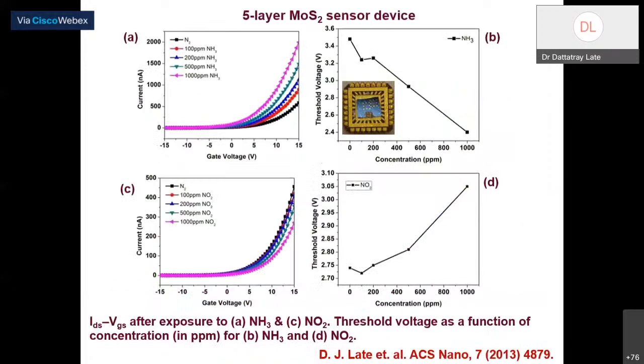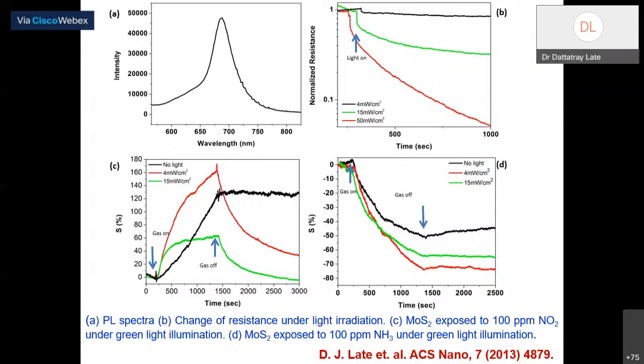One of the parameters which needs to be optimized is the response and recovery time. It's also very important when we have a functional device. So how did we optimize the recovery time? We used green laser light or red laser light. When I put the green or red laser light on the device, it helps to break the bonding between MoS2 and NO2 or ammonia molecules. I found in my experiment that we can tune the recovery time. That is very important, because in another 10 or maybe 100 seconds, my device is ready to sense another kind of molecule or gas, right?